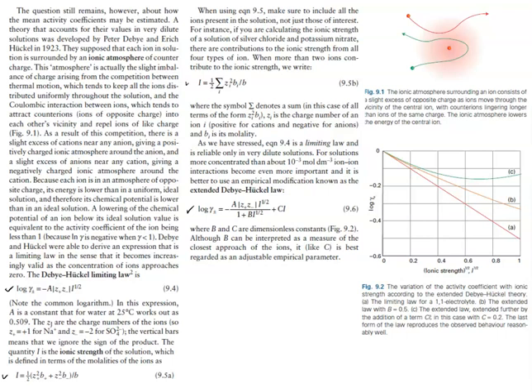So taking a look at figure 9.2, the variation of the activity coefficient with ionic strength according to the extended Debye-Hückel theory is shown: A, the limiting law for a 1-1 electrolyte; B, the extended law, where B equals 0.5; and C, the extended law extended further by the addition of a term. In this case, with C equaling 0.2, the last form of the law reproduces the observed behavior reasonably well.